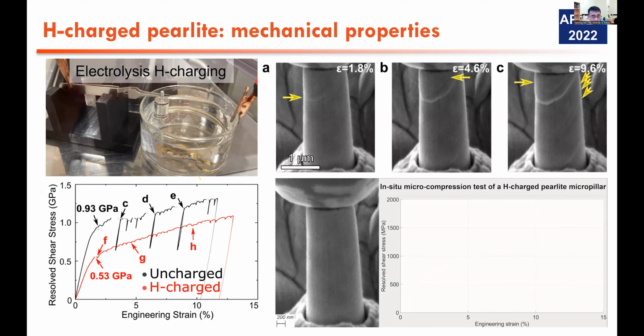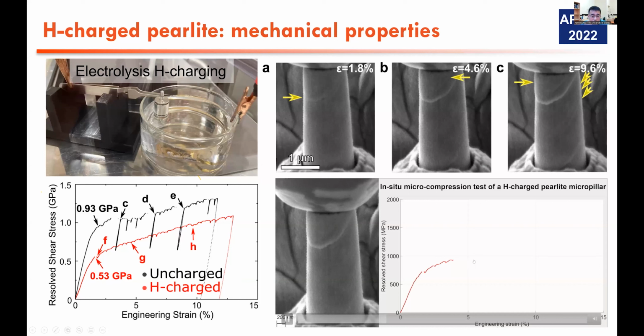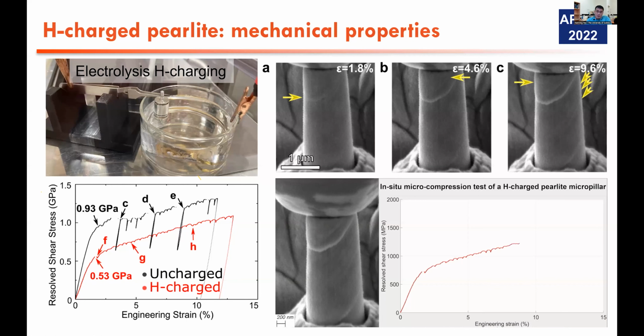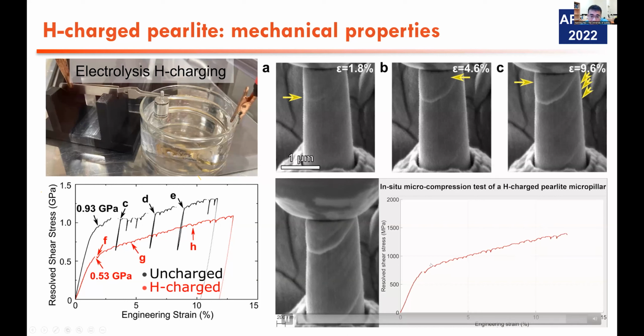Based on the stress-strain curves, we show a significant reduction of the strength, and based on the morphology of the stress-strain curves, we see the strain burst behavior is less significant, implying that the dislocations undergo fewer barriers for their motion.